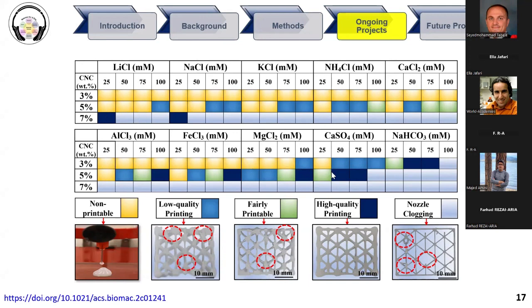And here in this table, we can find when we have non-printable or drop samples, when we have low quality printing, and what is the best concentration of salt and cellulose to have high quality printing. For example, if we increase the concentration of cellulose, we get nozzle clogging. So this table is so important for researchers in this field.